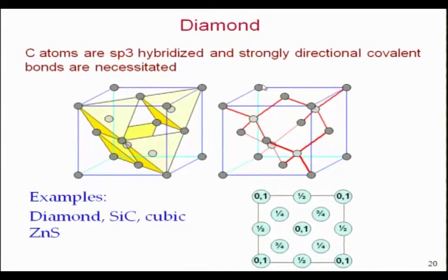They are also tetrahedrally coordinated, because if you keep the unit cell corner from dark grey to light grey, then what you will see is that the light grey will make an FCC unit cell and the dark grey will occupy the tetrahedral voids. So, basically the diamond cubic structure is two interpenetrating FCC lattices shifted with respect to each other by a vector 1/4, 1/4, 1/4.